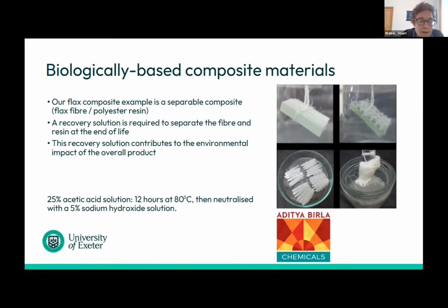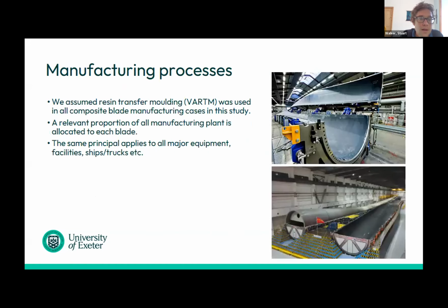And the recovery solution allows you to separate the two and then to treat them in different ways, as we showed earlier. But it does have its own environmental impact because we have to make that product. It has 25% acetic acid, so there's a reasonable environmental impact in making that separation product. Manufacturing process, we don't really need to worry about. This is just to show that we use the same manufacturing process. A common method, VARTM, was used in all the cases that we compared in our study.